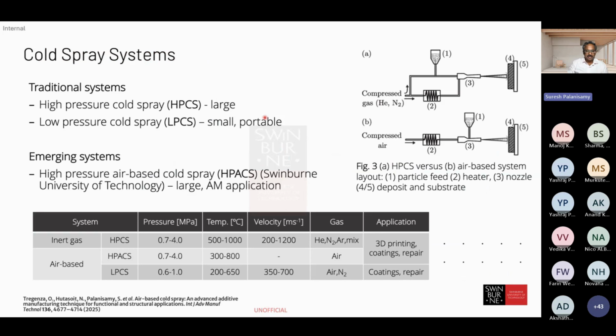Absolutely. That's a very important question, I would say, because the nozzle dimension, the nozzle pressure, and the design set a limit. I'm not going to talk much about nozzle design because that is itself a vast, big topic, but it plays a major role. And the velocity is obviously higher when you use gas at a higher temperature, as different gases can propel the particles faster. But the range is critical, and it will vary depending on the material and the substrate you are using, because you don't want to use high temperature with polymer applications or composite materials. However, you want to use high temperature for steels, titanium, and other materials which have a high melting point. So the dimension of the nozzle also plays a major role in that.